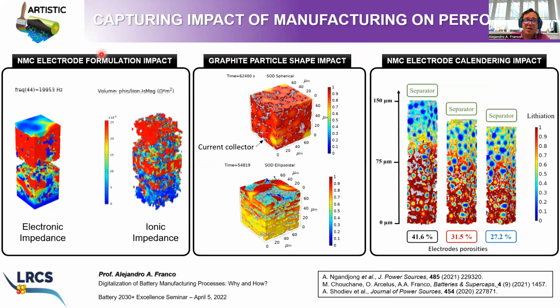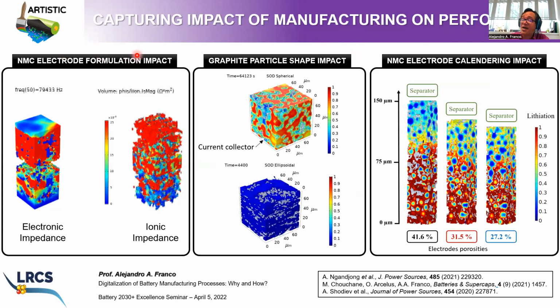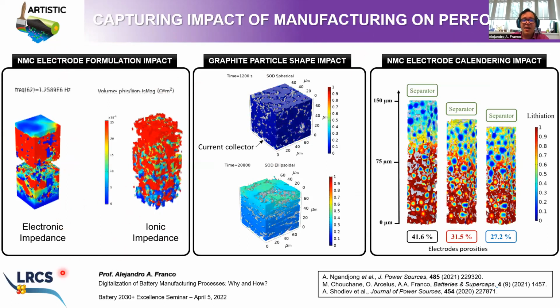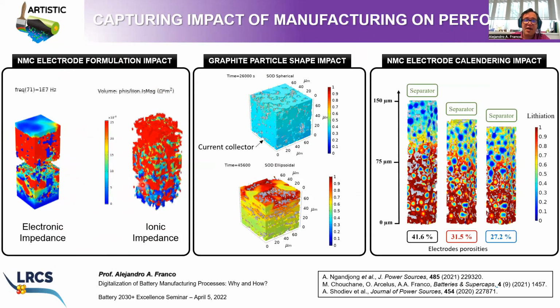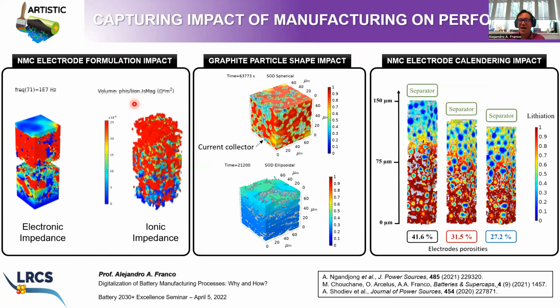And here you see the impact of formulation, for example, on an NMC electrode on impedance, on electronic impedance and ionic impedance. This is a simulated symmetric cell experiment. And you see that the impedance, both electronic and ionic, is highly heterogeneous, highly anisotropic, and the reason is that the CBD is located in a very heterogeneous, anisotropic way inside each of the electrodes, right?